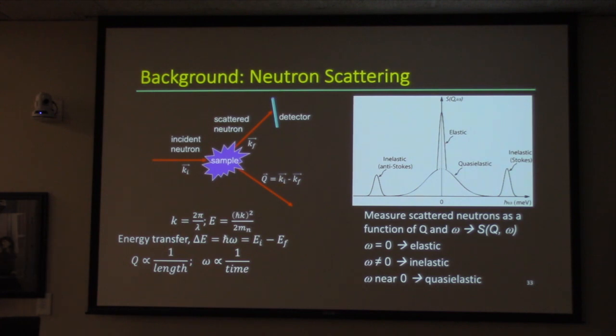This is the neutron scattering 101, only equations, I think. The important part is the experiments that we do turn out to be time of flight experiments. If it turns out that the incident energy and the final energy wave vectors are the same, then you get diffraction, and that's elastic scattering. But if it turns out that you transfer some energy either to the sample or the sample to you, then you do inelastic scattering. So you can measure those things, and those of you who have done Raman know that you can talk about the Stokes and anti-Stokes lines.